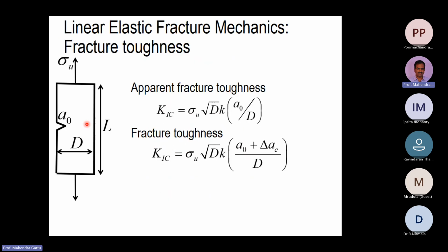But there is a catch here. In most of the laboratories, at least in our NIT-RKL, we don't have equipment to measure the crack growth. So we can only get the initial crack length, and we don't know the crack length at the peak load. So we'll be using our initial crack length while calculating the fracture toughness. And so this fracture toughness is called the apparent fracture toughness, because we are not actually finding out the crack length at the peak load.